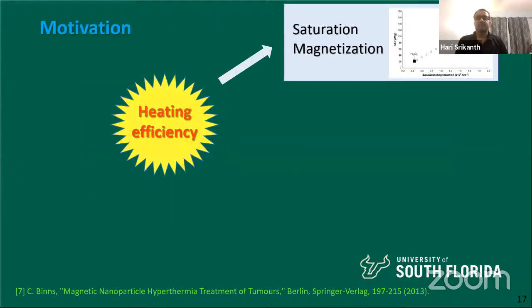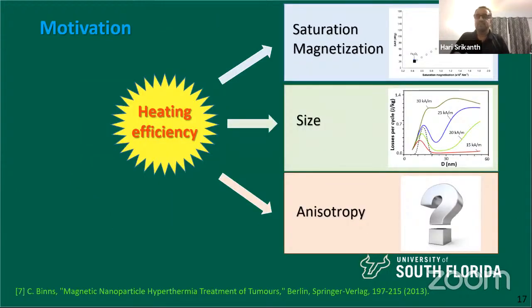All right, so now the first thing is you can increase the saturation magnetization, right? But it turns out that iron oxide is low compared to iron or iron cobalt. And guess what? Our hands are kind of tied here by the FDA because only iron oxide is considered biocompatible. This is the only approved biocompatible magnetic material that has been approved by the FDA for this treatment. So we have to work with this one material. We cannot just arbitrarily make any kind of magnetic material with large magnetization. So we have to work with one material. Iron, cobalt, we cannot do that.